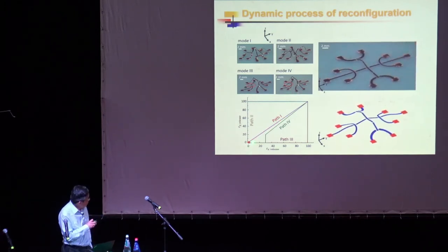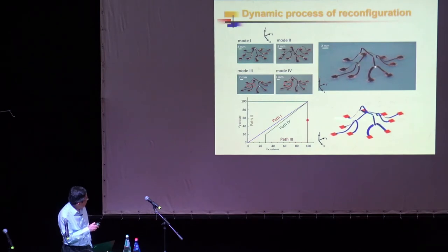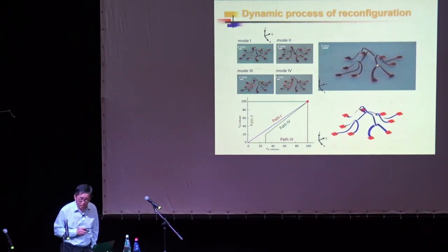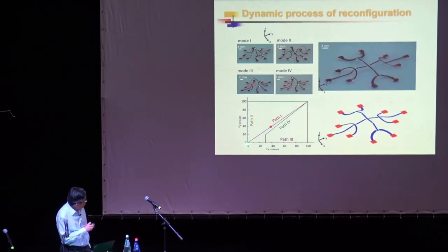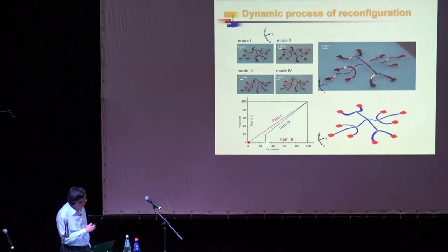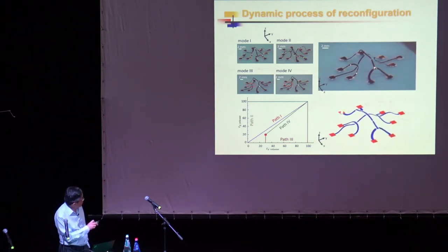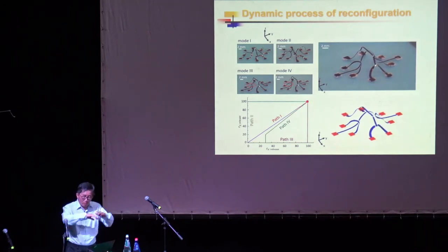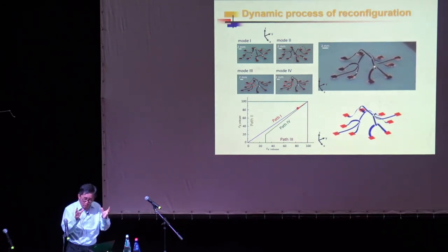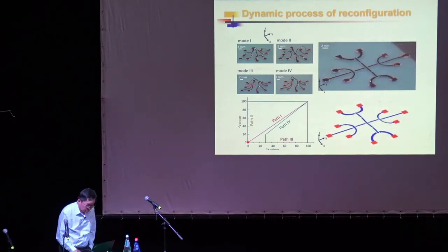And you can choose to reverse. This time, you release X first, followed by the Y release. So it's X release, now Y release. You can see this experiment, in theory, you reach the shape of mode number 3, the third mode. In fact, you can do more complex. You can release X partially, only 30%, Y then 20%, and you release the rest simultaneously. So you can then reach shape number 4. Okay? So it's really a very complex energy landscape. You can realize different buckling patterns by controlling the releasing sequence.